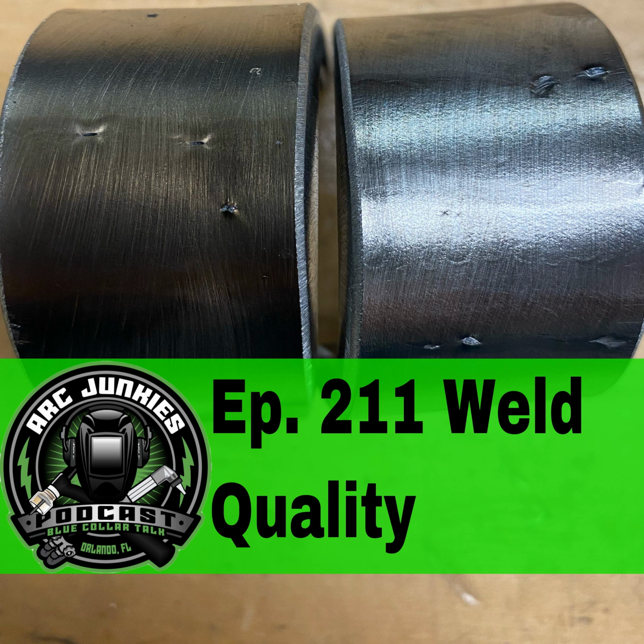Be very careful whenever you're loading a rod into your stinger, and be very diligent about the type of work that you're doing. I typically use two hands when I'm striking the arc, just so I can make sure I'm exactly where I want to be, and that electrode strikes off and fires exactly where I intend it to. Be careful and intentional when you're striking your arc. Just pay attention, and you can eliminate 90% of your arc strikes. If you do get your electrode stuck, the easiest way to fix that is to disconnect your stinger from your rod, let that rod cool down for a quick second, grab it at the base of the rod, and wiggle it back and forth. You don't have any electrical current going through there.